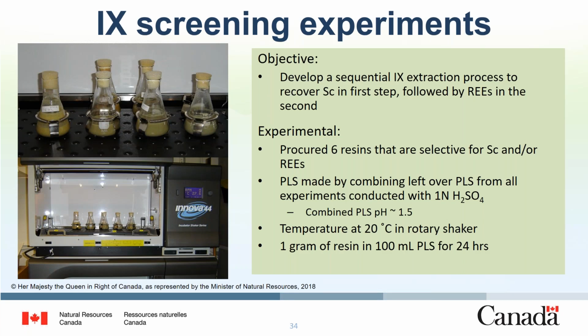The total RE concentration in the PLS is not expected to be above several hundred ppm, so neither direct precipitation nor solvent extraction are suitable technologies for recovering the REEs at these low concentrations. Ion exchange is considered to be the only viable option to us. The resin screening experiments consisted of 1 gram of resin with 100 mL of PLS in a flask and letting it mix for 24 hours.